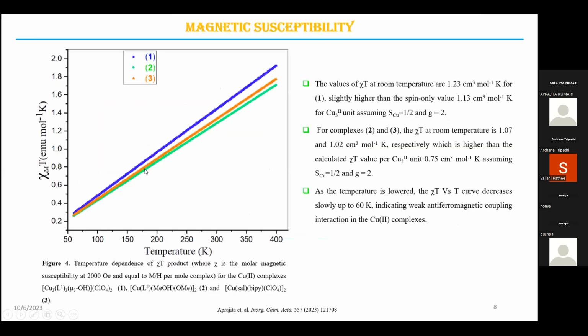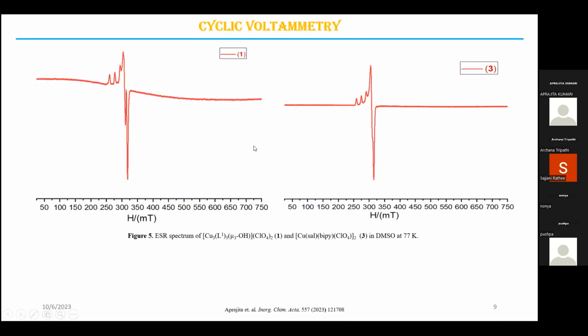Some properties were studied. First, the magnetic susceptibility as a function of temperature was studied in the range of 60 Kelvin to 300 Kelvin. As the temperature decreases, the product of magnetic susceptibility and temperature, chi-T, decreases slowly, which shows a weak antiferromagnetic coupling interaction in the copper complexes. Also, the room temperature value of chi-T was slightly higher than the calculated spin-only value.